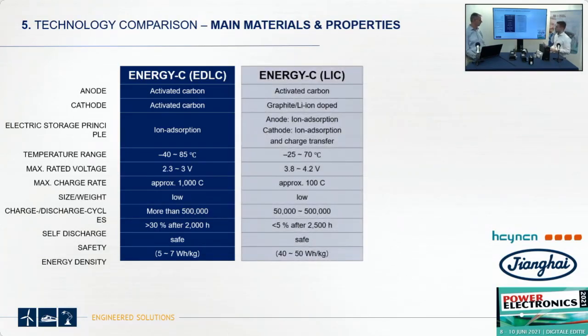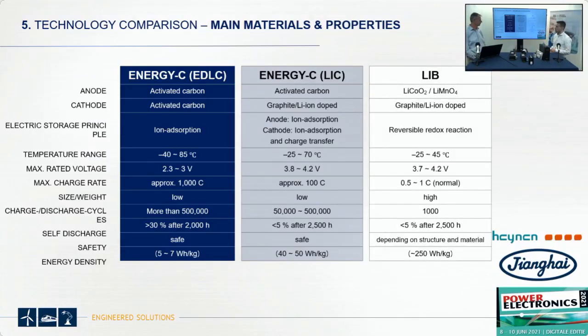With lithium-ion capacitors, you have the benefit of high cycles, but with a reduced charging rate. It's high compared to batteries, but it's less than EDLCs. The benefit from this technology is the much higher energy density, between 40 to 50 watt-hours. And batteries have the typical disadvantages: low cycle numbers, low charging rate, and the safety for lithium-ion batteries is under discussion.